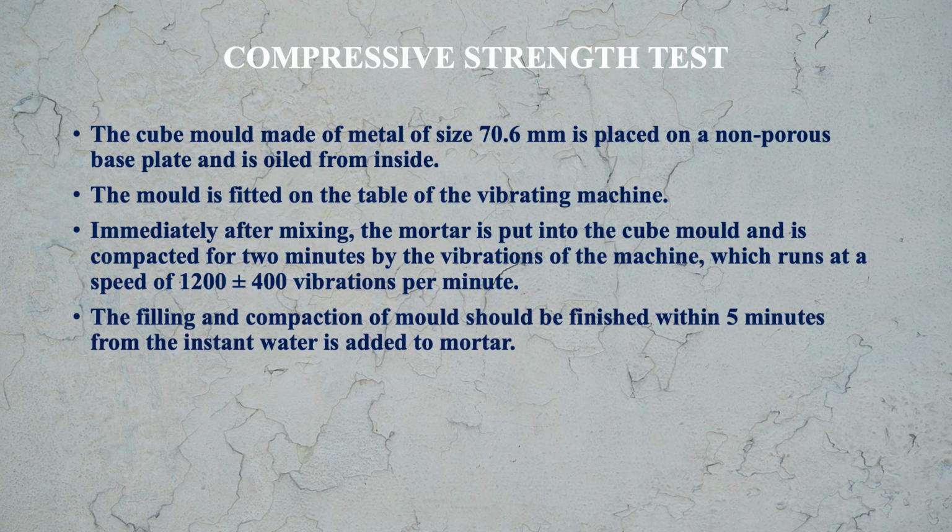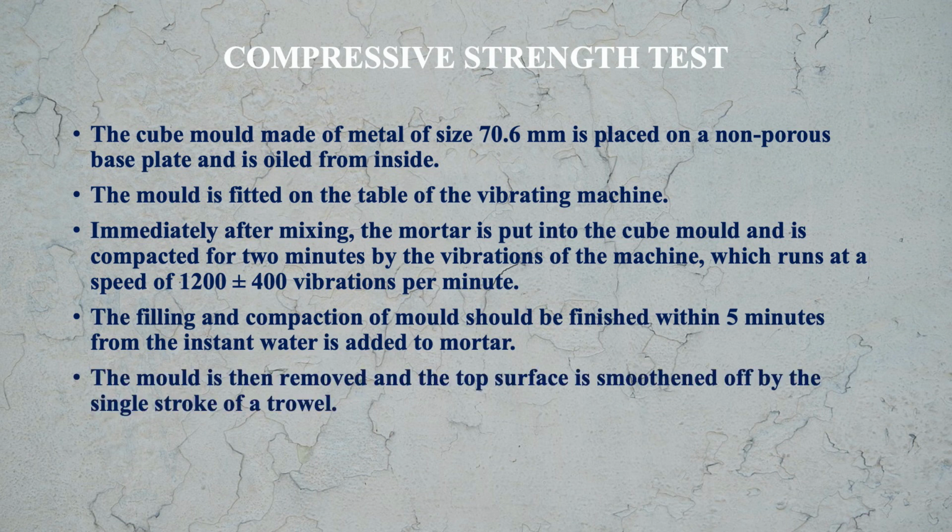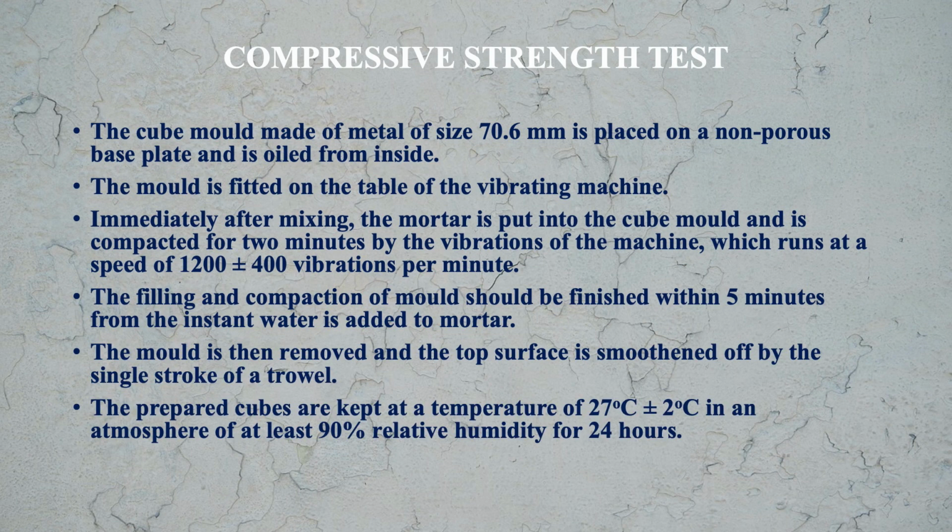The filling and the compaction of the mold should be finished within 5 minutes from the instant water is added to the mortar. Now the mold is then removed and the top surface is smoothened off by a single stroke of the trowel. Now the prepared cubes are kept at a temperature of 27 degrees centigrade plus minus 2 degrees